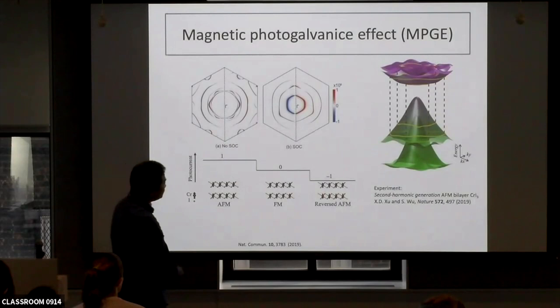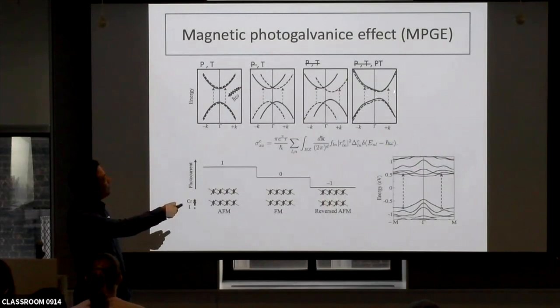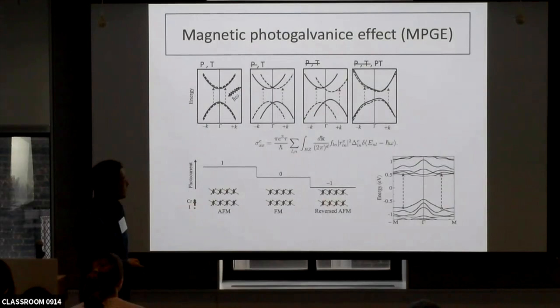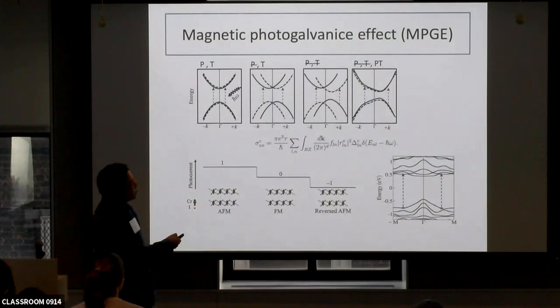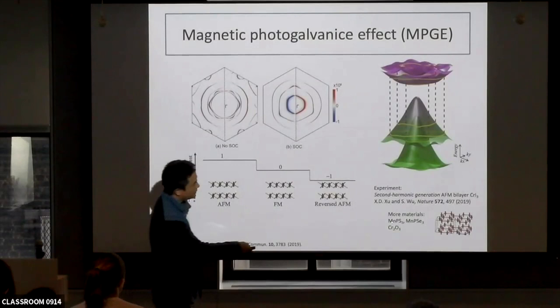When I talked to several experimental groups, I was told this material is very insulating, and even if you have a photocurrent, you may not be able to measure it easily. This is a demonstration of the photocurrent from band transitions. Without SOC it is perfectly symmetric. When you break the symmetry with SOC, we get a non-zero net current. The DC current is a second-order response, like second harmonic generation — they share the same symmetry. A recent experiment by X.D. Xu and S. Wu measured the second harmonic generation of exactly the same system and got exactly the same symmetry. For this mechanism, I only need the K/-K symmetry breaking — I don't need an insulator. Even a semimetal or a PT-symmetric Dirac semimetal works, as long as P and T are both broken.